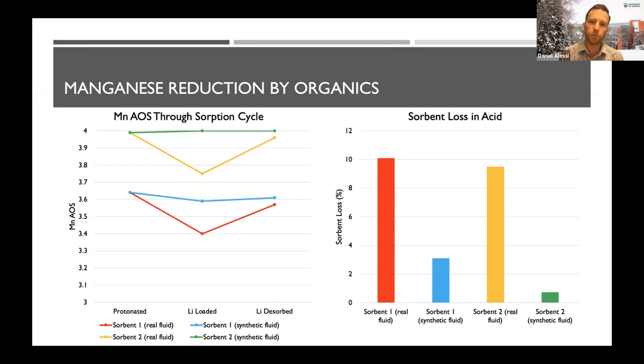We wanted to investigate at which step this manganese loss was happening, right? So we have the initial dry sorbent that's sitting out on the bench. We put it in the brine, it's reacting with the brine. And then after that, we put it into an acid, and that's the lithium desorption step. And that's what you see here. So we have a protonated sorbent. That's the sorbent in its initial condition before it sees the brine. Lithium loaded, that's when it's in the brine and it's being loaded up with lithium. Lithium desorbed, that's when it's exposed to the acid and the lithium's kicked back out into solution.